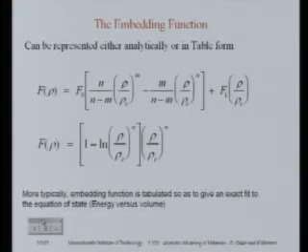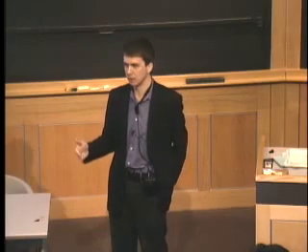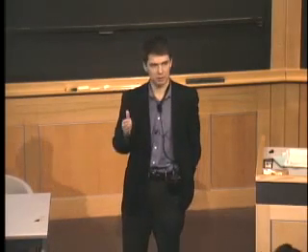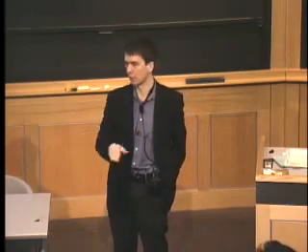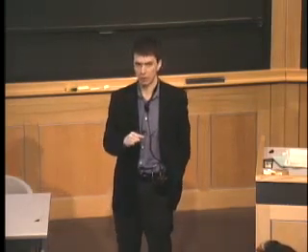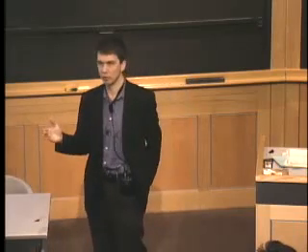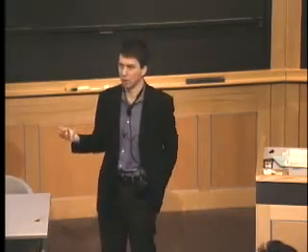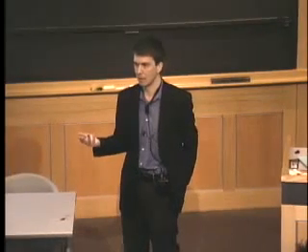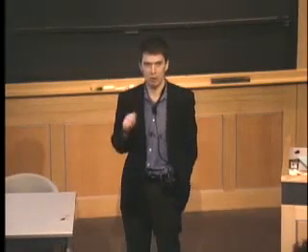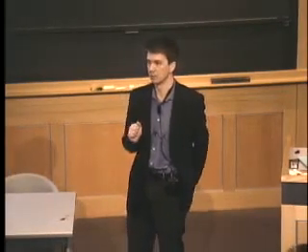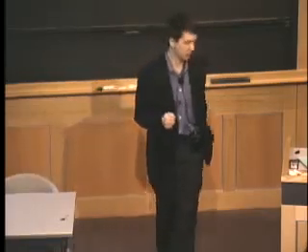More and more now what people simply do is tabulate the embedding function. And really what they do is they tabulate it so that you exactly reproduce the equation of state. What is the equation of state? The equation of state is energy versus volume or lattice parameter. Okay? So say at every lattice parameter you could try to get that energy with a better method, say quantum mechanics. Okay? And then fit your embedding function so that you exactly reproduce that. Okay? And so often the embedding function is tabulated.